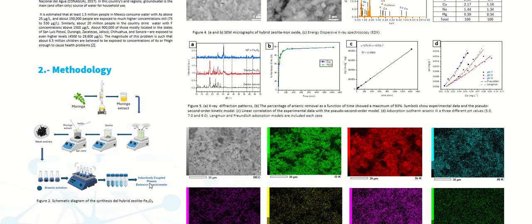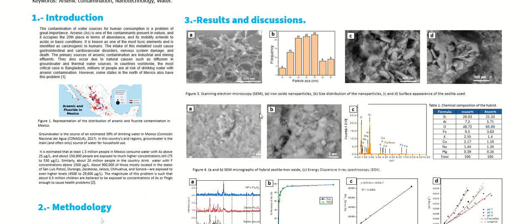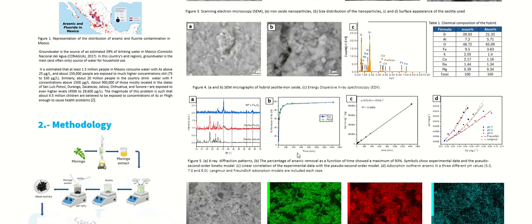Characterization results. Figure 3 shows scanning electron microscopy: Sections A and B, iron oxide nanoparticles; Sections C and D, surface of the pristine zeolite. Figure 4. Sections A and B, surface appearance of the zeolite iron oxide, and Section C, energy dispersive X-ray spectroscopy, and Table 1, chemical composition of the hybrid. Figure 5. Section A, X-ray diffraction patterns of zeolite, zeolite iron oxide, and iron oxide nanoparticles.